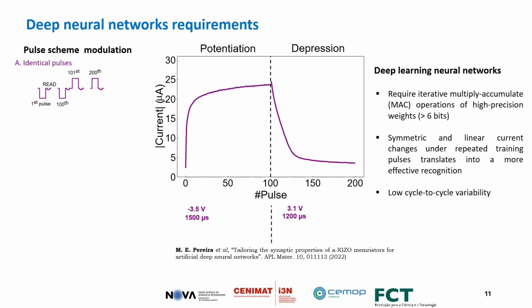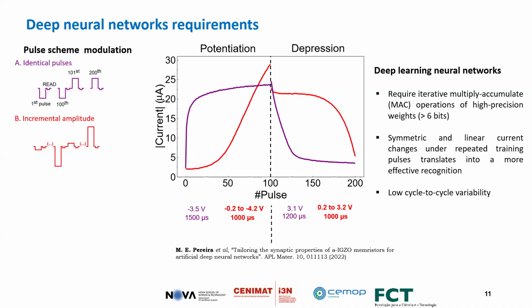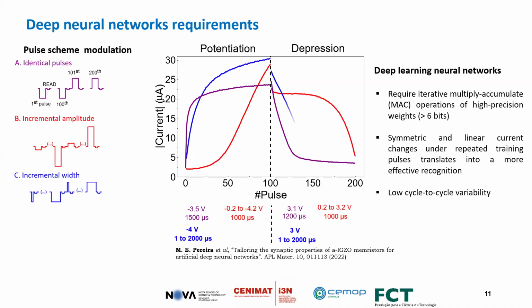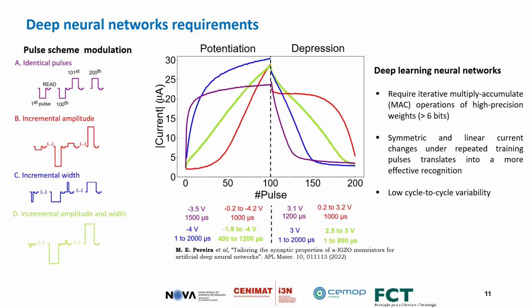Then we started a very nice study together with Maria Pereira, my former PhD student, who is now a successful scientist in this regard. We started to have pulse scheme modulation, so different pulse schemes. For example, incremental amplitude of the pulses, and then incremental width. So we change the width of the pulses, and then at the end we started to have another paradigm, incremental amplitude and width. We see that if we change the width and the amplitude of the pulse, we actually can have a very nice linear and symmetric response. And this is nice, so we published this.